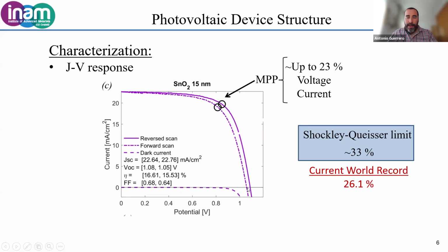In our laboratory, using tin oxide as a selective layer, we can get up to a maximum of about 20% efficiency. In our lab, we have measured devices from other labs up to 23% efficiency. And this efficiency is calculated from the maximum power point. So it's calculated from the power that can be extracted from these solar cells.